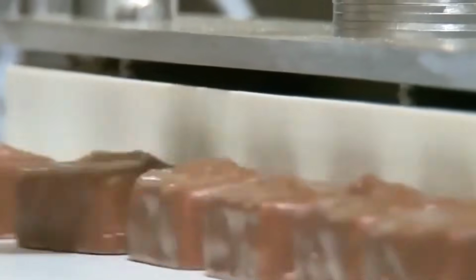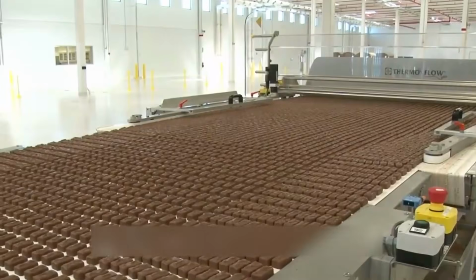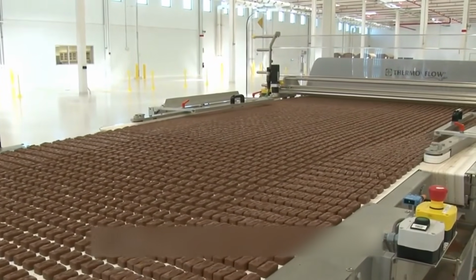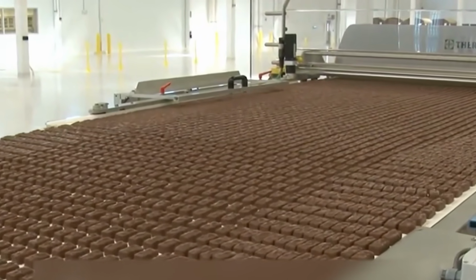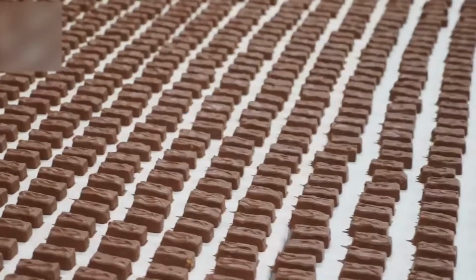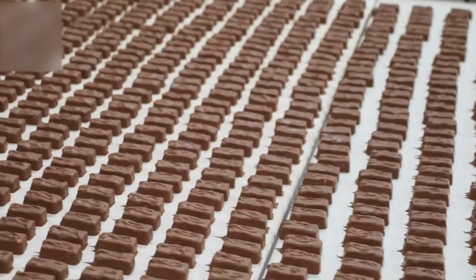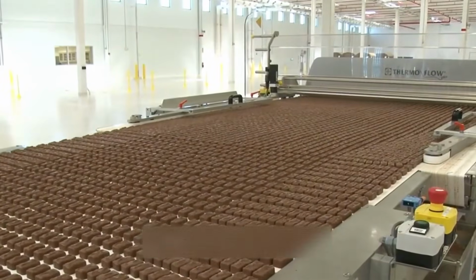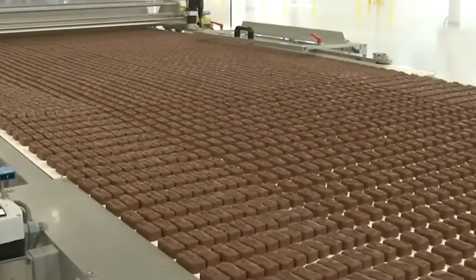Cooling sets the chocolate and stabilizes the final bar. The first zone sets the surface quickly so the coat does not slump. Subsequent zones cool more gradually to promote stable crystal growth and reduce bloom risk. Cooling also brings the internal nougat and caramel to a stable temperature. If bars exit too warm, the coating can scuff in wrapping. If too cold, the coating can crack under wrapper folds.